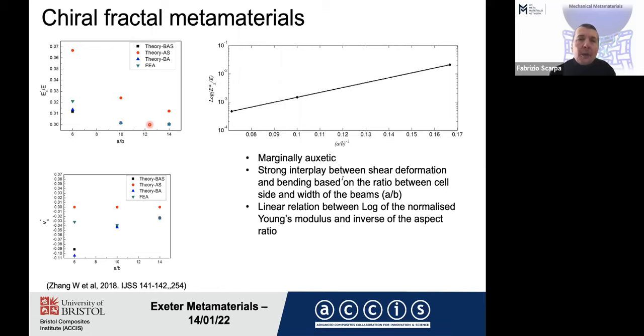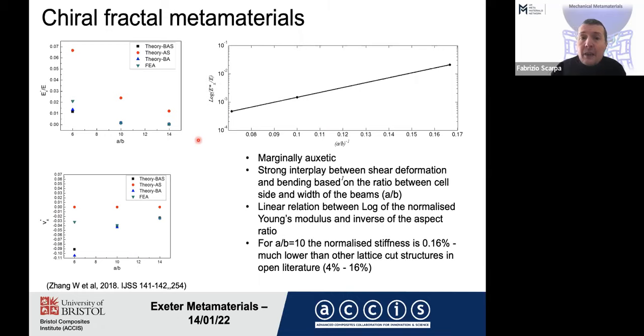Something that is also quite interesting is that if you plot the logarithm of the normalized Young's modulus versus the inverse of this ratio A/B that defines the fractal configuration, you will have a perfect line. And this is an excellent indication that, like fractal physical quantities, this type of configuration has this type of exponential variation of the mechanical properties with the order. And this is, again, typical of fractal units.